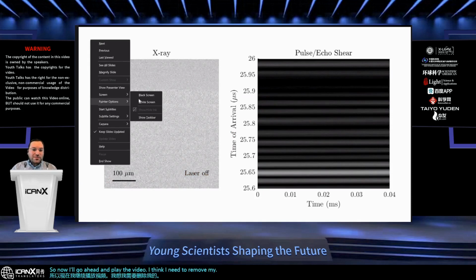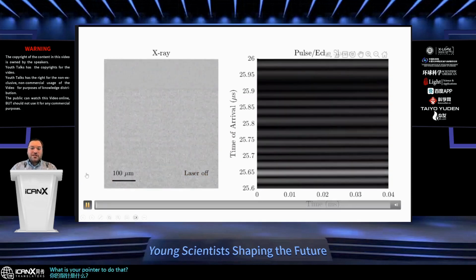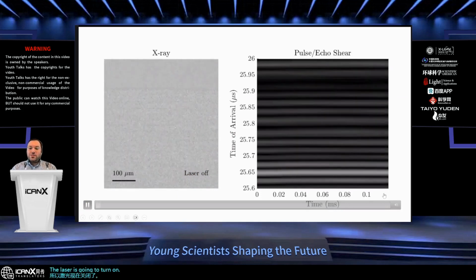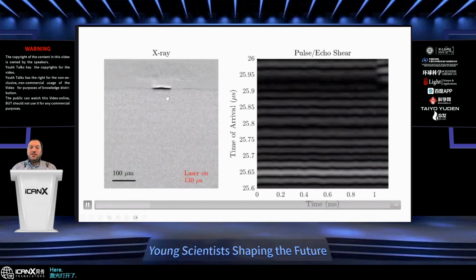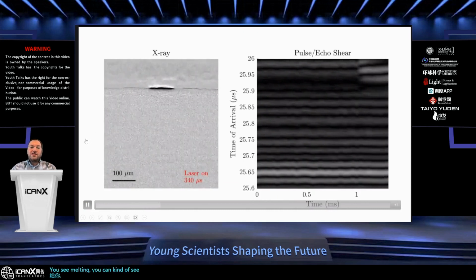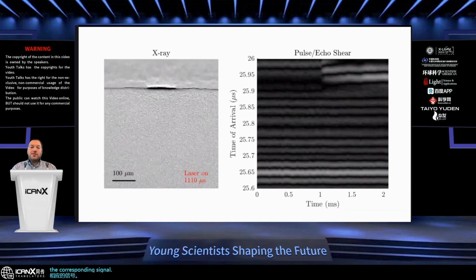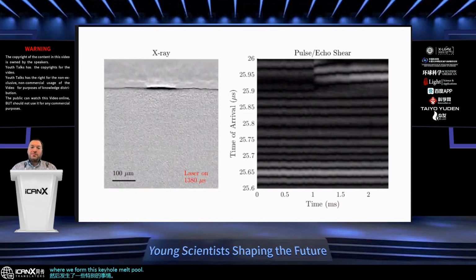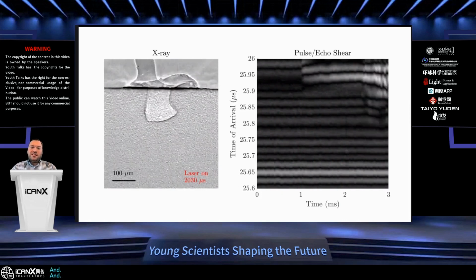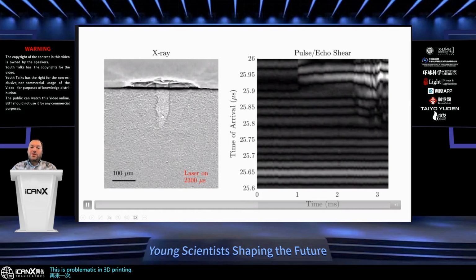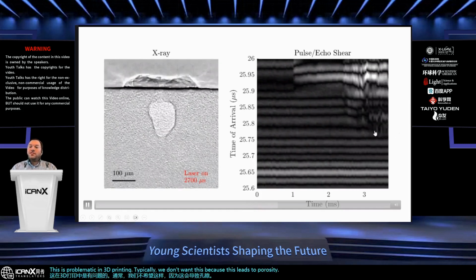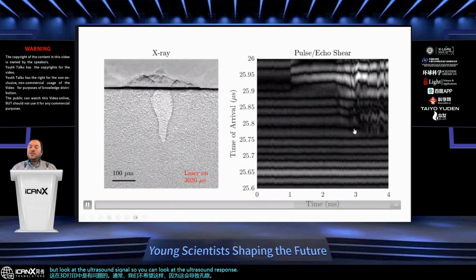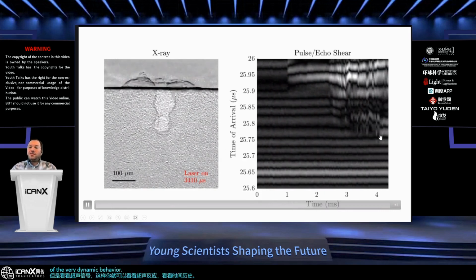I think I need to remove my laser pointer to do that. So the laser is off right now. The laser is going to turn on at 1 millisecond. This is the ultrasonic response. The laser's on here. We see melting. You can kind of see the liquid formation there, the corresponding signal. And then something special happens where we form this keyhole melt pool, right? So we form a vapor region. And again, this is problematic in 3D printing. Typically, we don't want this because this leads to porosity. But look at the ultrasound signal. So you can look at the ultrasound response and see a time history of the very dynamic behavior of the melt pool.